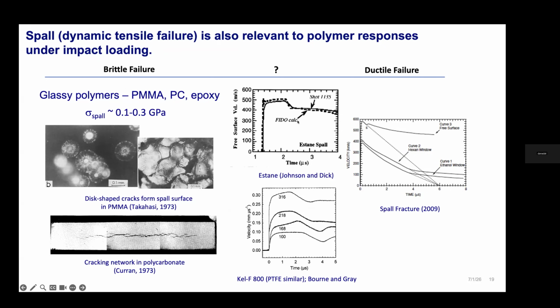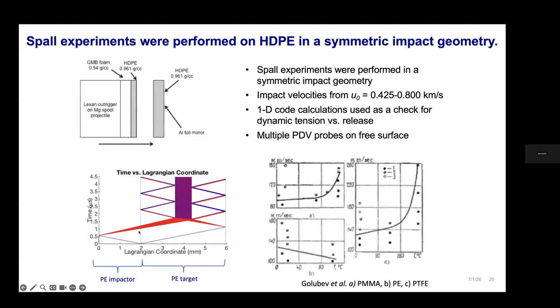But then there are a lot of other polymers where we just have shock wave profiles and not any recovery work. And there's a big question about what is happening in these materials, right? You don't see a pullback signature, you just see what looks like drawing behavior. When you see the release, you don't see a pullback that would indicate shock reverberation in a scab, like you would see in a brittle failure mechanism.